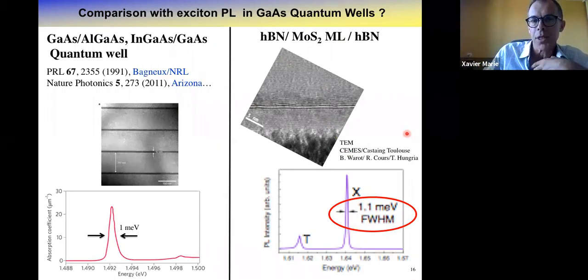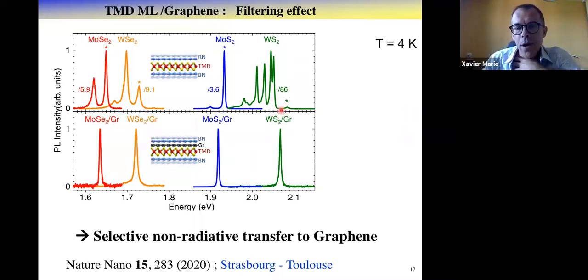Just a recent result we had in collaboration with Stéphane Berciaud in Strasbourg was to build a basic hetero-bilayer, made of a TMD monolayer and a monolayer of graphene. And here is the PL spectra of these monolayers, just the TMD encapsulated in hBN with the narrow lines. And we see at lower energy many lines due to exciton complexes, trion, dark exciton, whatever. And when you take the same TMD monolayer coupled to a graphene monolayer, everything encapsulated, you get a filtering effect. Basically, you keep only the neutral exciton emission.